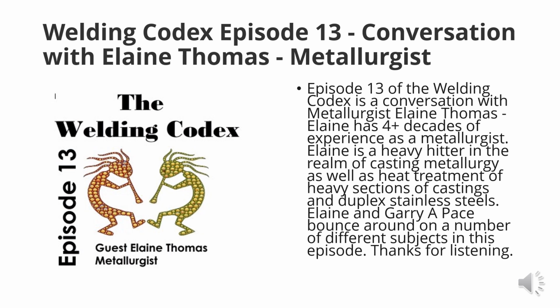Okay, let's talk about the G48 testing. What does the G48 test get me? G48 testing, in my opinion, is really something you would do to say, this is what this alloy is capable of doing. I've seen a lot of people use it to qualify a heat or a heat treatment of a part, and there are many different practices in there. All of them are pretty hairy. I think using it as a test, like method A or B, for the weld and heat affected zone is probably a legitimate use of it, because you can tell whether you've gotten rid of the sigma phase, or if you're doing no post-weld heat treat, you can tell whether you have a lot of sigma phase in your weld and heat affected zone.